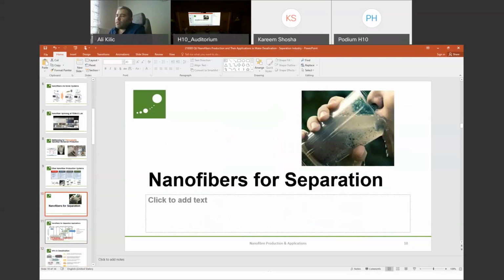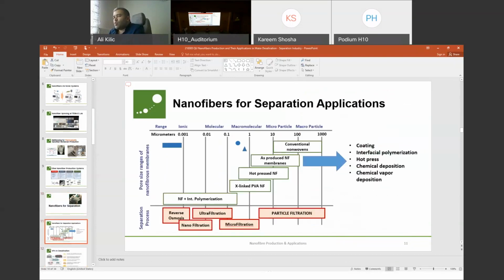So what can we do with nanofibers actually? We are working with Dr. Javaid also on this. If we check the conventional nonwovens, these are the substrates used in membranes. We are able to reduce the pore sizes down to 10 micrometers, so they are not so good for membrane applications. If you go to nanofibers, even going down to 50 nanometers, since they have fibrous structures, it is quite difficult to reduce the pore size lower than 1 micrometer. So please keep this in mind.